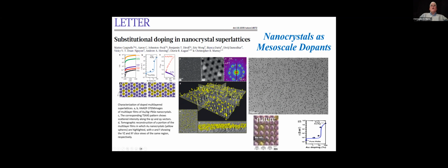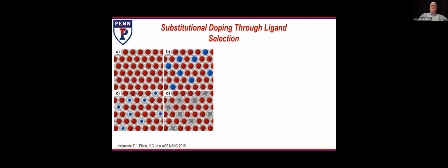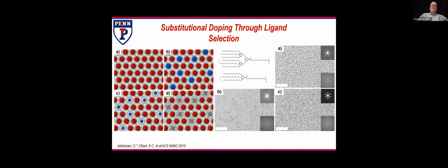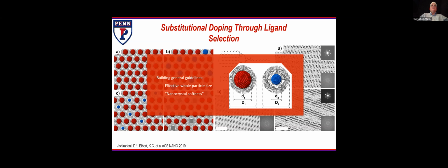But the key here is that we have a strategy now for the introduction of materials of different compositions that helps to separate the organization and the assembly from the underlying inorganic nanostructure's geometry. And in this piece, we have an example here where the surface chemistry is being modified with different types of supramolecular ligands, so dendrimeric and other related constructs, so that you can begin putting together systems. In this particular case, it was putting square pegs in round holes, but basically you can use the organic chemistry and the interactions between the head groups to anchor the materials and the tail groups to control their organization, so that you can begin to have design freedom in terms of the geometries and sizes of these structures.